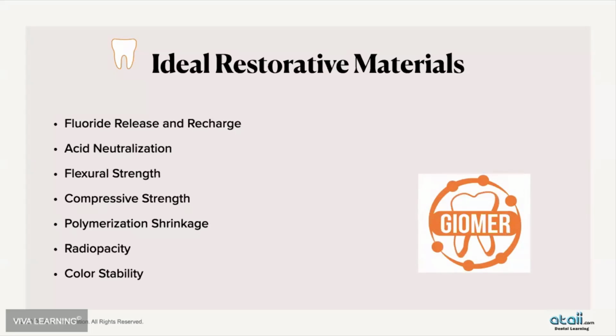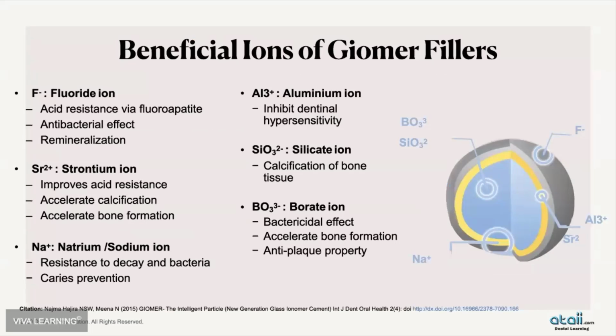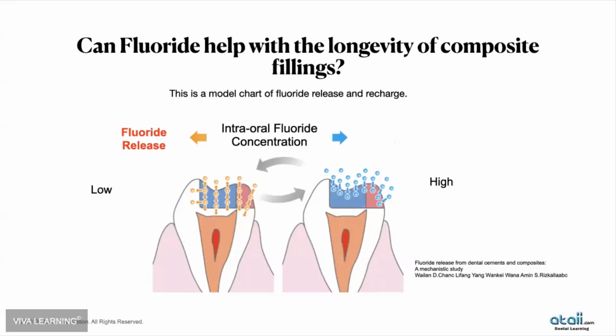Well, the Giomer technology has all of these in it. What does that mean? A Giomer product that I've been utilizing, and Shofu's been at the forefront of having those filler materials, has the fluoride ion. It definitely has an antibacterial effect. It remineralizes. Most importantly, it's acid resistant because of the fluorapatite, and it is strong, and it does not shrink, and it inhibits any dental hypersensitivity. So the Giomer fillers have, as you can see, the fluoride ion, all the sodium ions and silicate ions and borate, all of these that are needed for the longevity of the composite, and for it not to discolor, not to have sensitivity, not to shrink, and ideally to allow that fluoride to come back.